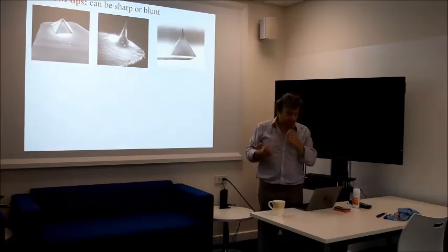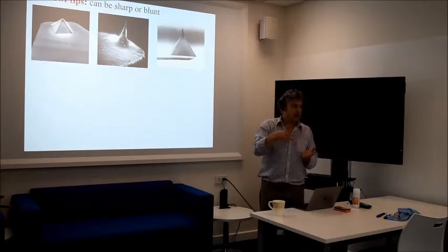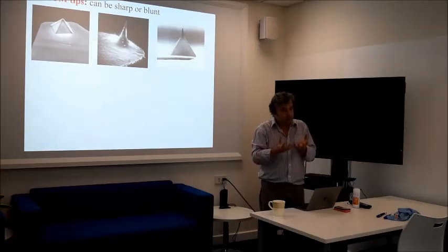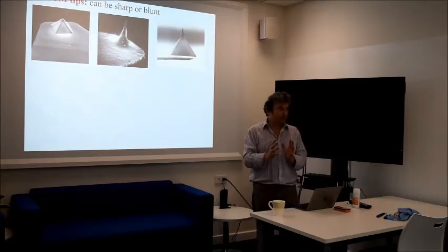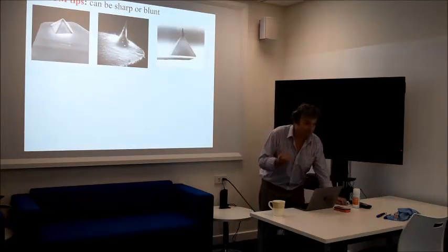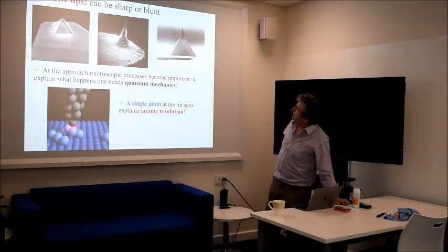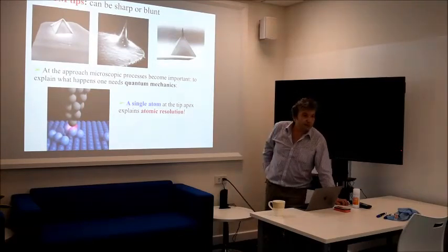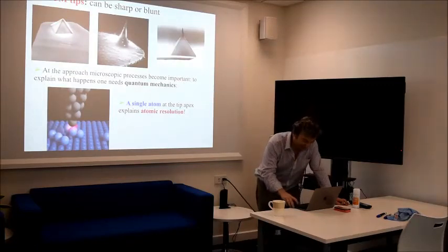So what they do, they sometimes just crush the tip upon the surface. Maybe Mark told you about this. And this creates some atoms coming on the tip, or the tip is losing some of the atoms. And they discard it. They do it many, many times until they see a nice image. And when they do, they try to keep that tip, not crushing anymore, and scan for some time, like a month or maybe one day. It depends. But these are images of some of the tips taken with another microscope, another kind of device. So these are real tips, and you can see that there's something sharp.